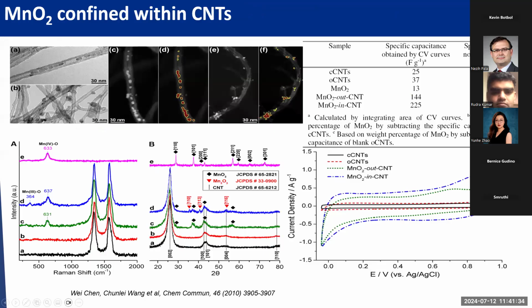So that's one research. And another research I want to address is we can add manganese oxide nanoparticles inside the carbon nanotube to actually create composite materials with a nano-confinement effect. Because this carbon nanotube we use here is purchased from a commercial company. And it's about, I guess, 20 nanometer diameter, and the inner diameter is about 10. If you can put manganese oxide particles like what we achieved, those nanoparticles have a really uniform size because it's confined by the inner diameter of carbon nanotubes.